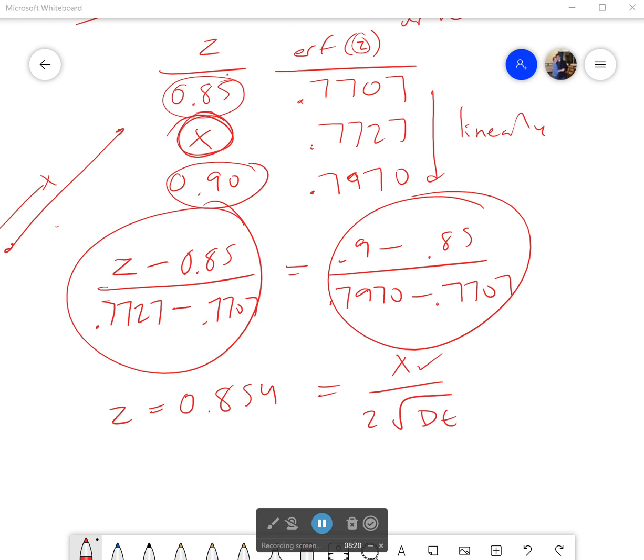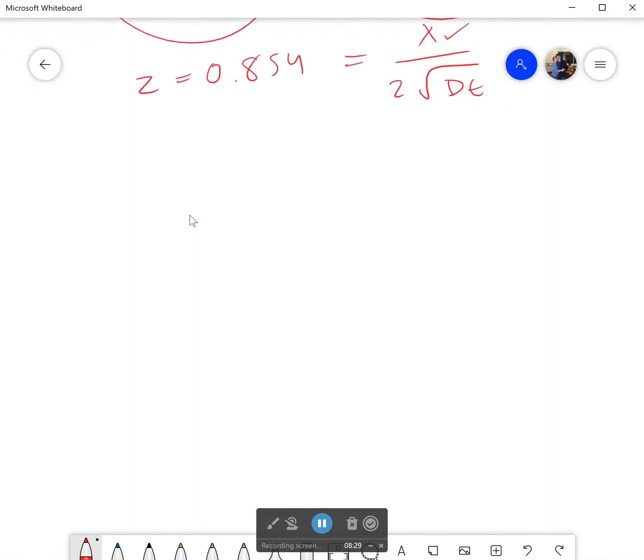But it told us that we could pull that data from table 5.2. Now, why do we need to pull it from a table? Why don't we just have like a number for diffusion? Well, it's because remember that diffusion coefficient D is actually temperature dependent. It's a function of temperature. And it looks something like this. We have D naught, then exponential of negative Q over RT. Second thing is that temperature is Kelvin, not Celsius. So to go from Celsius to Kelvin, well, I have a thousand degrees Celsius. I'm going to add 273 to that to get to Kelvin.